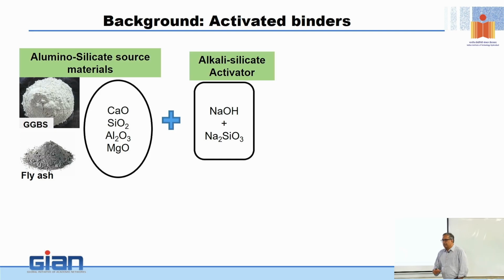And we activate these materials with an alkali silicate activator. We use an alkali, sodium hydroxide, that creates a high pH environment. The high pH is required to dissolve the glass in these two materials so that it releases the silica and alumina, which I can then use to form binders. Now, we may or may not use sodium silicate. The idea of using sodium silicate, also called water glass, is to supplement the silica that's available in these two materials, because oftentimes the available silica is not sufficient for the formation of the binder. So that comes from the sodium silicate, which is typically added in solution form.